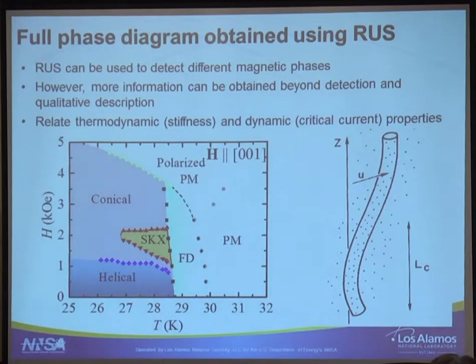The other thing is that we want to relate the thermodynamic aspect with the dynamic, with the critical current properties. And borrowing, for those who know, this is a picture from Blatter's review, this is for vortices, but the nice thing of all these theories about pinning is that as long as you don't say what this line is, you can have the same models. You have a linear object that is elastic interacting with a pinning center. So a lot of what we know from pinning of vortices, we can apply, remembering what's the true nature of the Skyrmion phase.